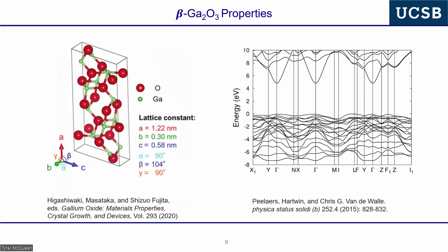Yeah, okay. And so I always forget the numbers, but the a lattice constant is about 12 angstroms. The b lattice constant is very small. It's about 3 angstroms, and the c lattice constant is about 5.8 angstroms, okay? And the beta angle is significantly different than 90 degrees. So it's really monoclinic, and it's really not like any other crystal structure.